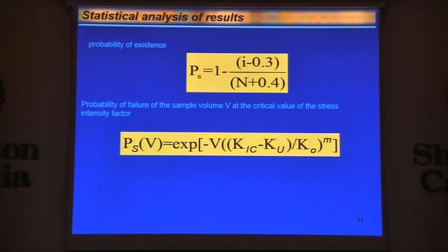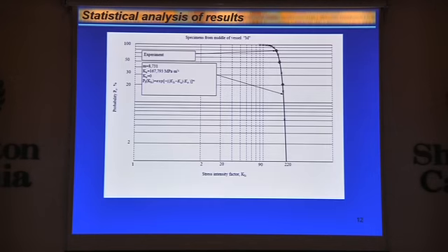where the probability is 0, and this is the mean value, where the probability is about 64%. When you put all these experimentally measured values, here we have 3, and if you use this formula, you can calculate through this point. You get the Weibull distribution, and from it you can get the lower bound and the highest upper value within the probability range of 99%.